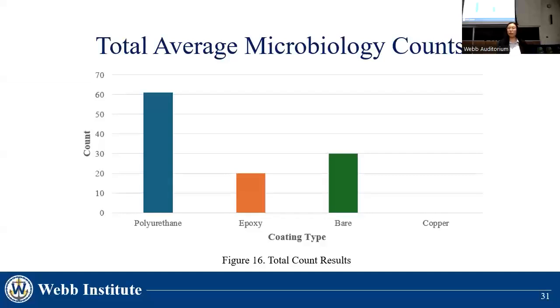On average, between the 2 primary trial plate sets, 61 microorganisms were seen on the polyurethane plate, 20 on the epoxy plate, and 30 on the bare plate. No growth was recognized on the copper control over the length of the testing window.